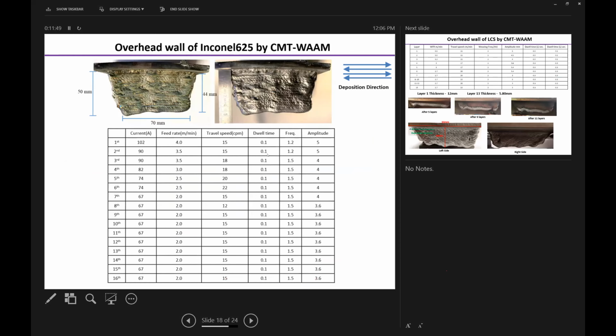So at the end, we were able to fabricate a wall of a maximum height of 50 mm and a length at the end of 70 mm by using Inconel material. But the surface finish of the deposited wall was not good.